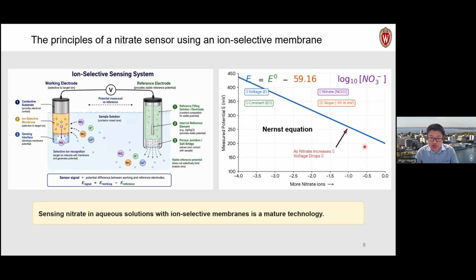So based on the negative charge, we can plot a relationship of the potential or the voltage of the reference and working electrodes against the nitrate concentration. If we plot this on a log scale, we're going to get an idealized linear response. That means the higher the nitrate concentration, the more negative your electrode. Based on that, we can detect the nitrate ions in an aqueous solution.